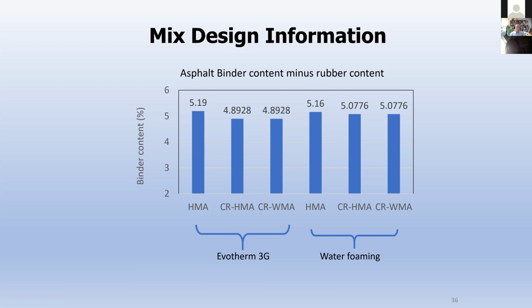That's something we care about. For example, in one project here the asphalt content is 5.19. This is the new asphalt content we are using, 5.19. But we use rubber for this material here, and you can see it becomes like 4.9 or so, 4.9 basically, with the crumb rubber. Because we have rubber inside, we really reduce the amount of asphalt.